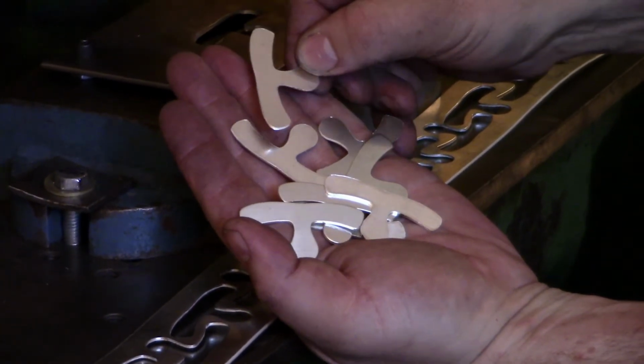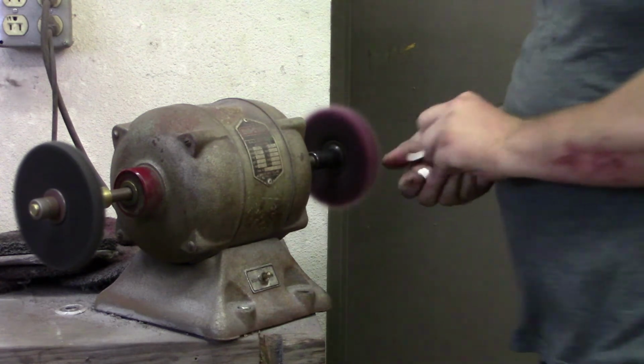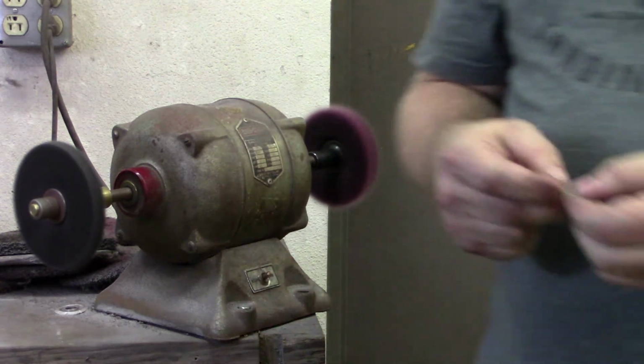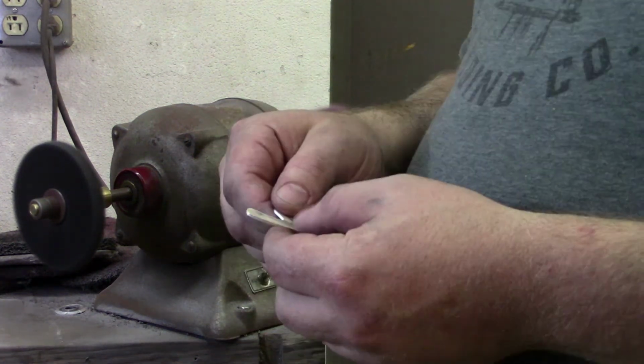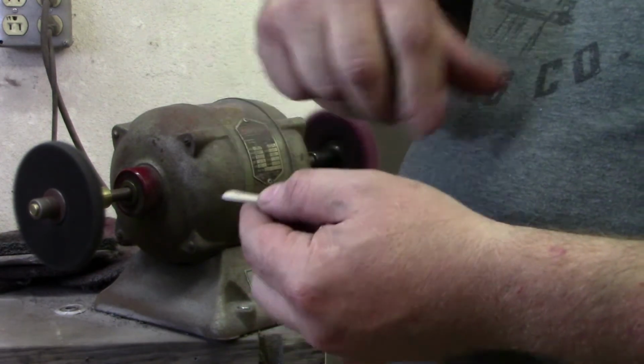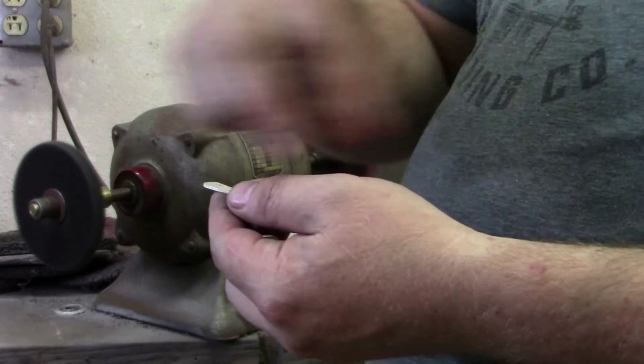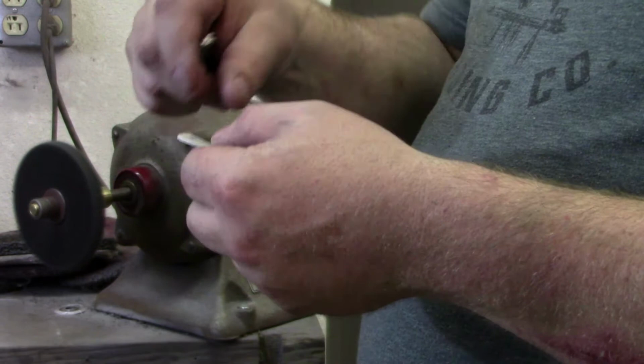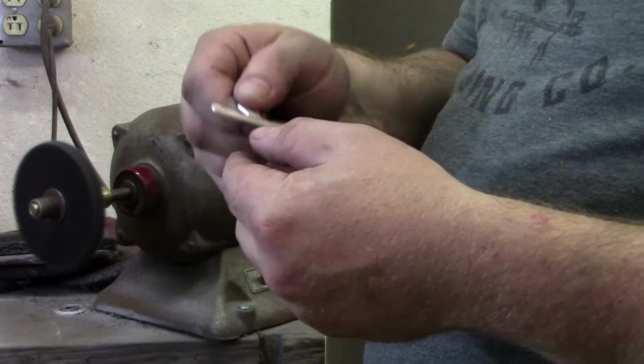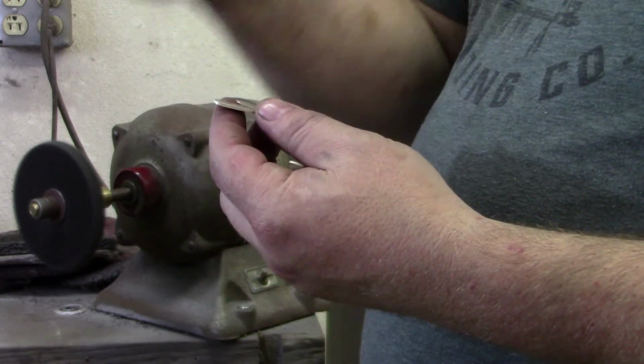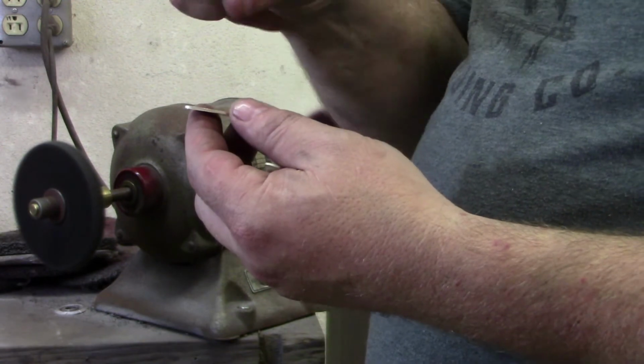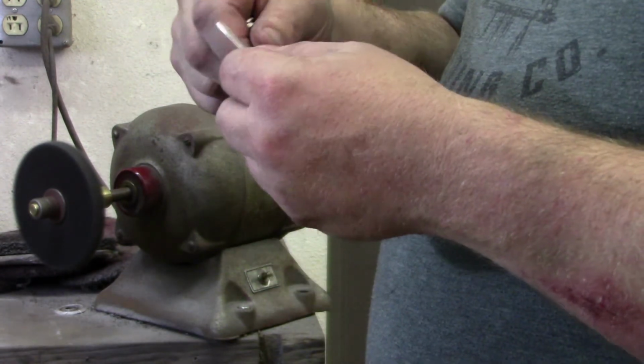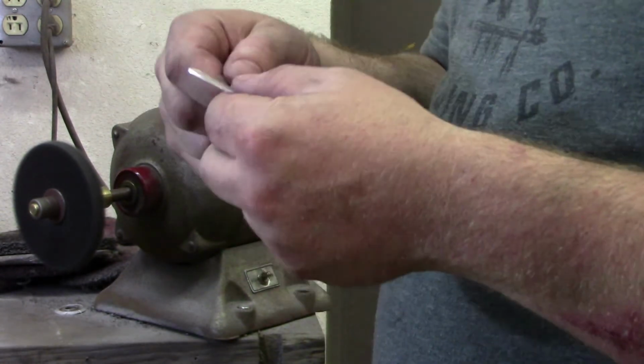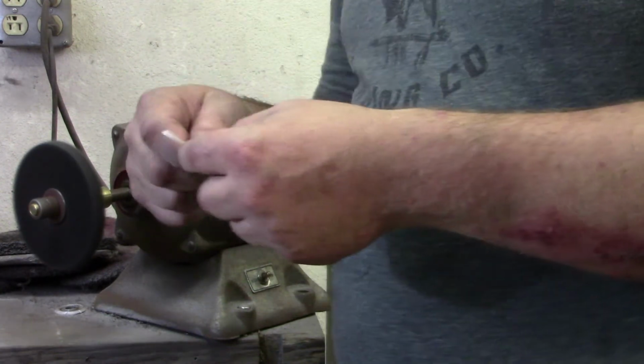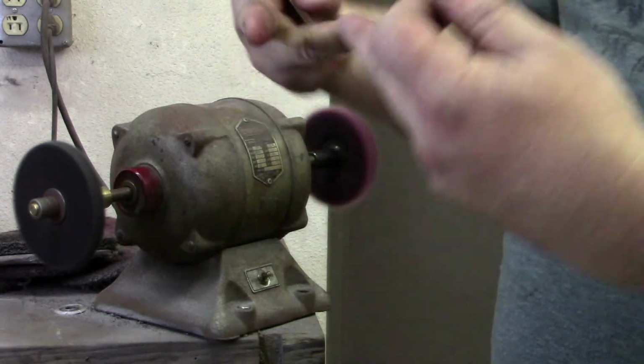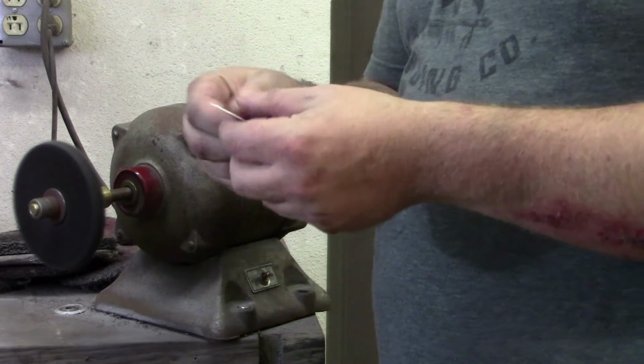That's the starting blank. I've just got those blanks that we blanked out, and I annealed them. What you're doing when you're annealing is that grain structure gets all elongated and mixed up and changes all the shape. And when you anneal it, you're actually splitting all those grains into tiny little pieces. And so that's why you take all that effort of getting the correct reduction ratio and flipping the strip and making sure that all those grains stay intertwined.